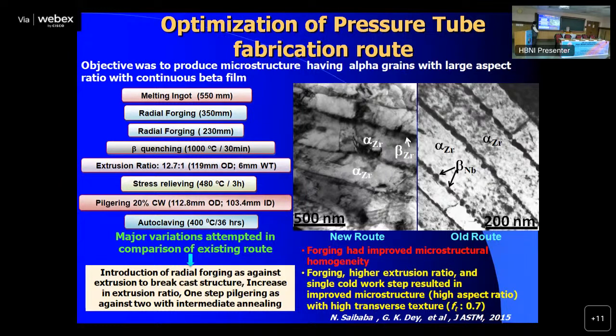There is an increase in extrusion ratio, and one-step pilgering as against two with the intermediate annealing. So these are the three important changes compared to the old flow sheet. That led to forging and a higher extrusion ratio, and a single cold work step resulted in improved microstructure, high aspect ratio, and high transverse texture. These are attributes very similar to that of the Canadian pressure tube. So our microstructure is now very similar to the Canadian microstructure.